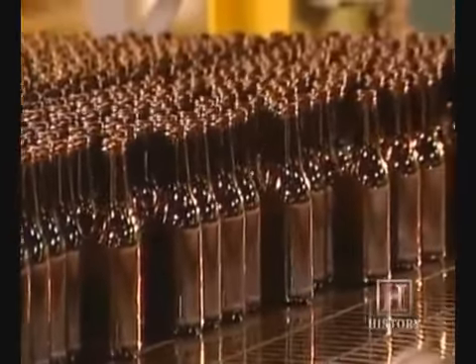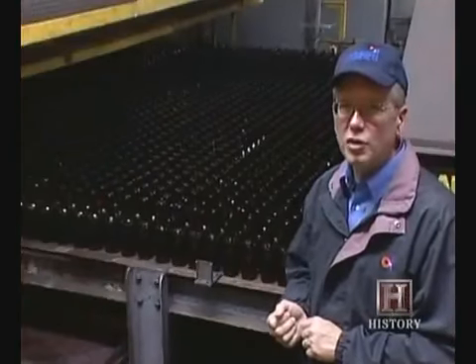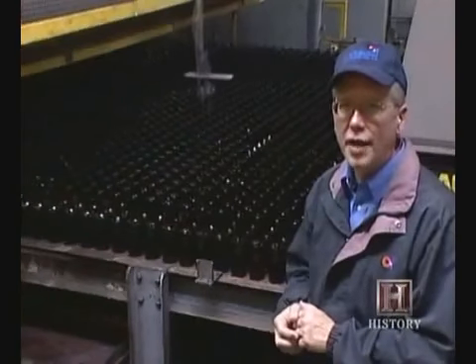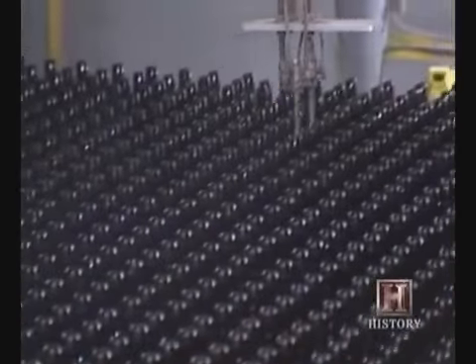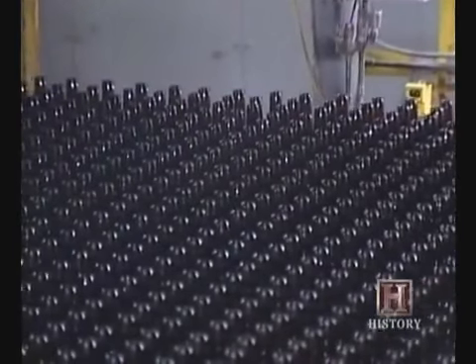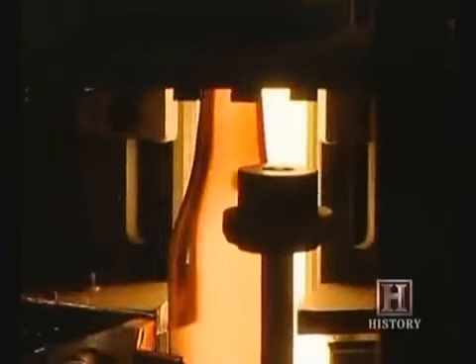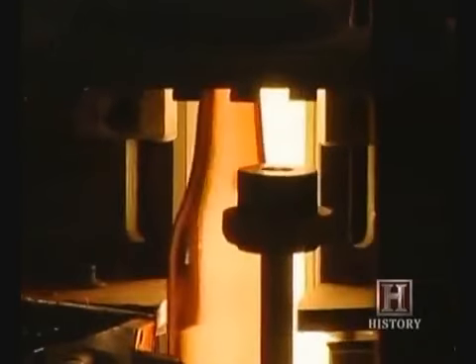After the annealing process is complete and the bottles have cooled down to about 200 degrees Fahrenheit, we apply a coating on the outside of the bottle. The coating protects the bottles against abrasion and scratches, thereby enhancing the strength characteristics of the container. Each bottle is inspected. Those that don't pass get sent back to the fire.